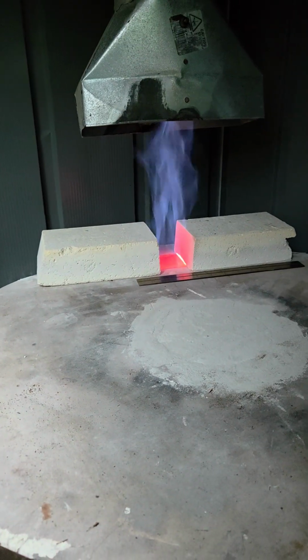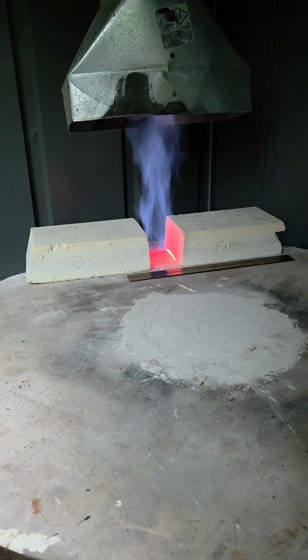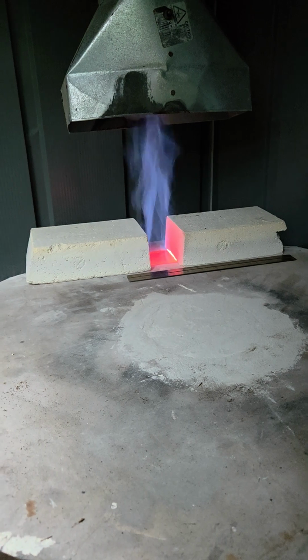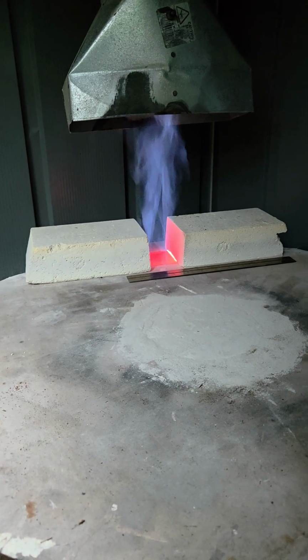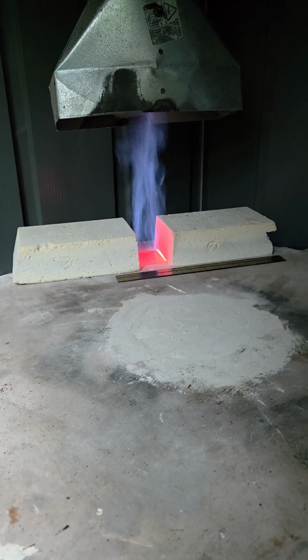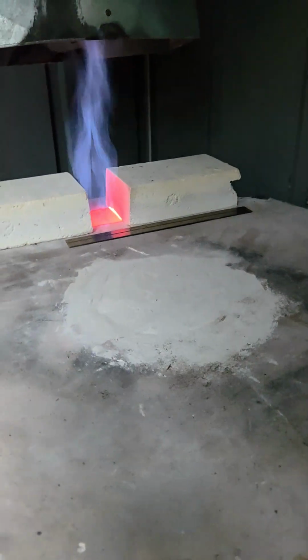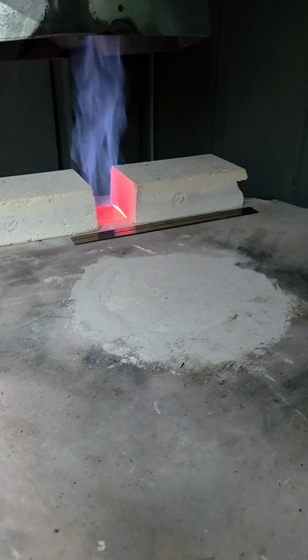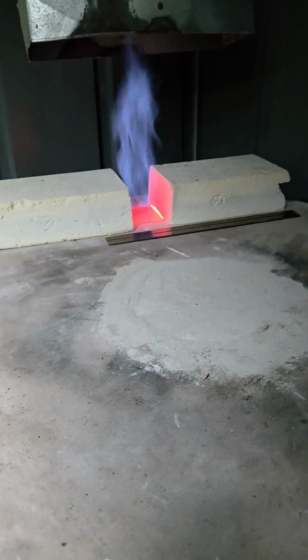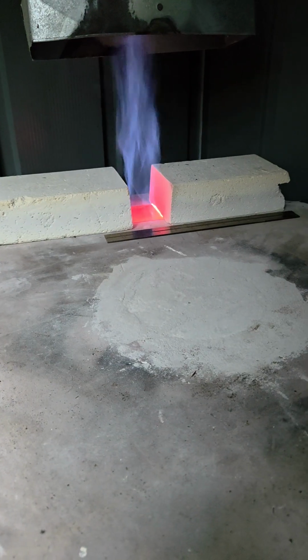So this is the reduction flame now. The temperature did go up slightly, so I reduced the gas pressure down to, what did I reduce it to? It is 1.85, so I reduced it by 0.05. And the temperature now is kind of stabilizing at about 931.5 degrees.